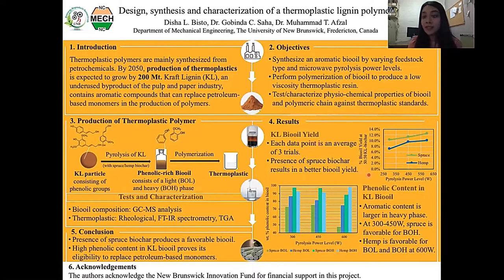The varying factors affected our bio oil yield such that with increasing power level, the bio oil yield also increased. Additionally, in the presence of spruce biochar, the bio oil yield was larger as compared to when hemp biochar was used. With the gas chromatography and mass spectrometry analysis, it was observed that the phenolic content was over 90% for most of the heavy phase bio oil.